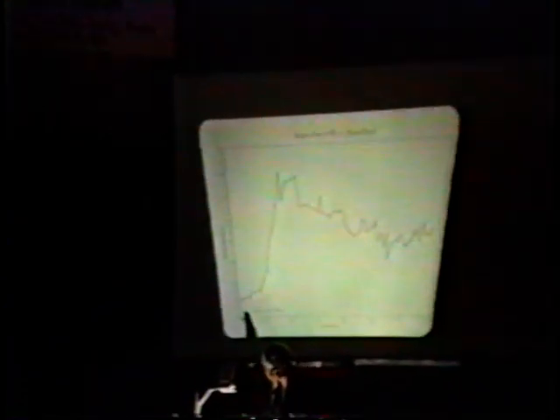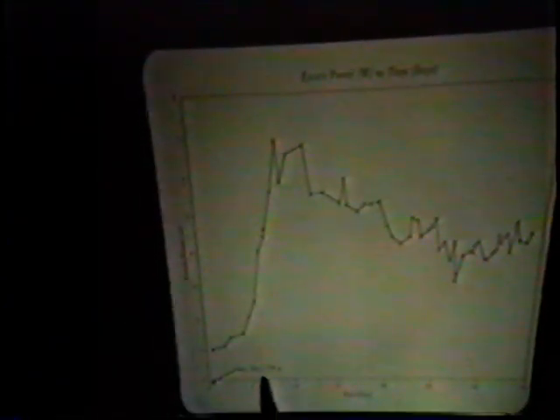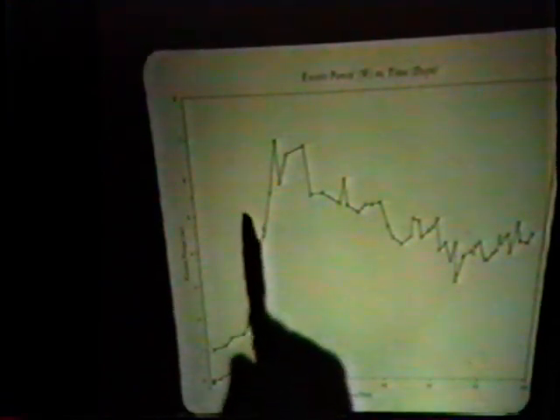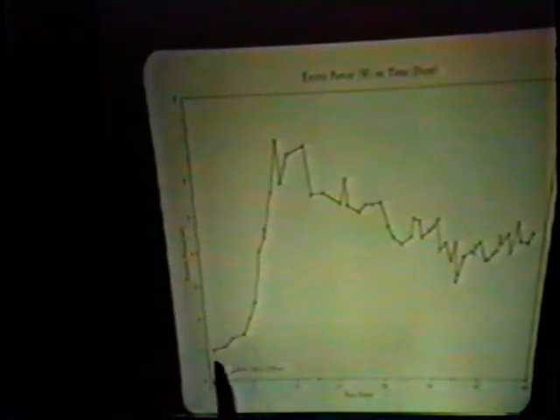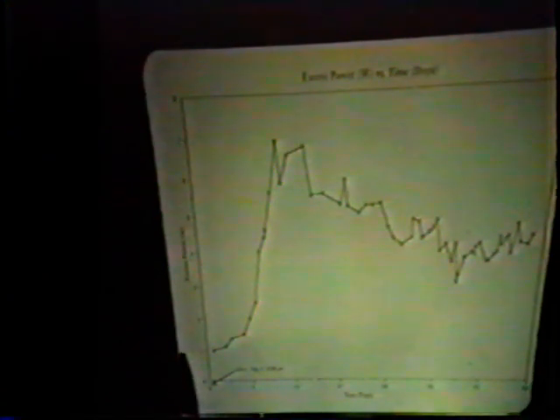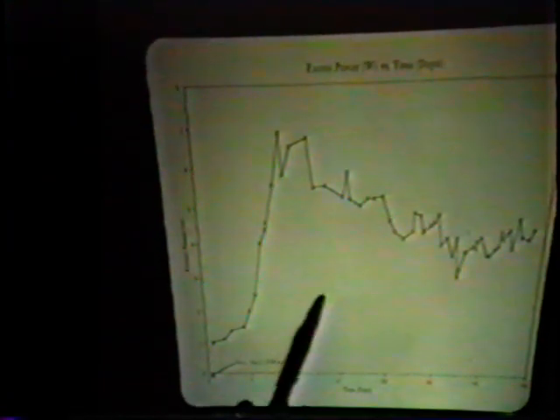Okay, now why did it recalibrate? Well, let me show you this excess power versus time curve. You can see that here, the zero point was about May 5th, and this rapidly climbed up to about 7 watts of excess power. And over here on the 2nd of May, we had a little explosion, a hydrogen explosion. Basically we were running the cell, we looked at it one day, the thing was bubbling like mad, which meant the recombiner wasn't working all that efficiently. Dr. Eagleton tried to put some more recombiner in, just a small amount, to get the recombining reaction going better.